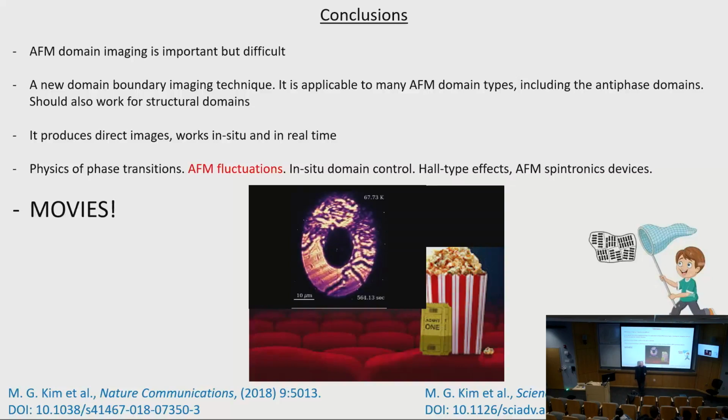curvature of the domain boundary and its fluctuations, right? So high curvature is supposed to be high energy domain line, and we typically see that the high curvature regions move easier, right? So this is consistent. And flat regions, they move, but not as vigorously. A lot of things to analyze here. A lot of information in those images, but maybe not enough for establishing the scaling laws.